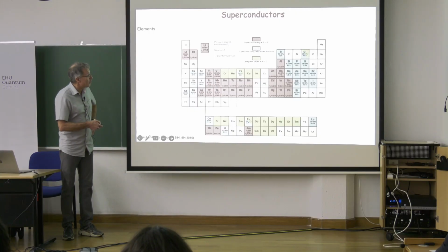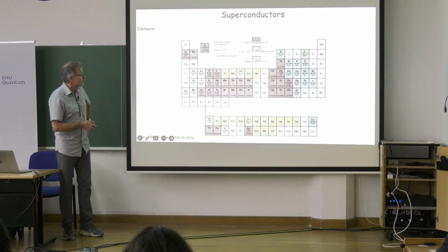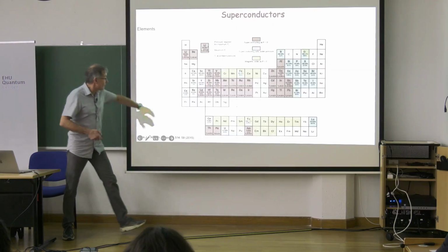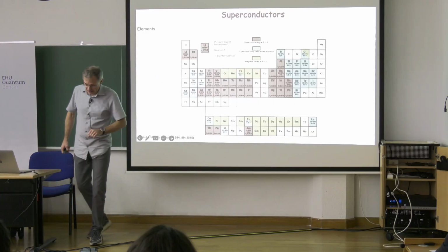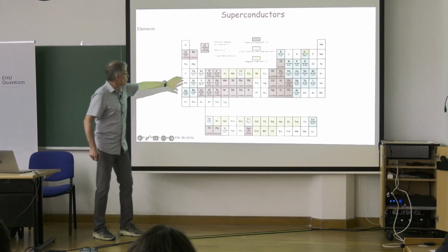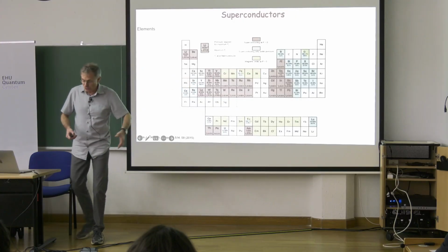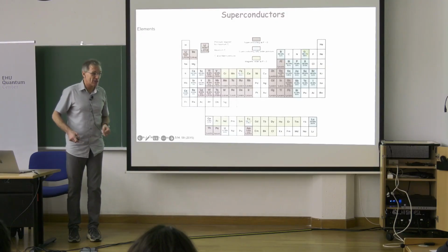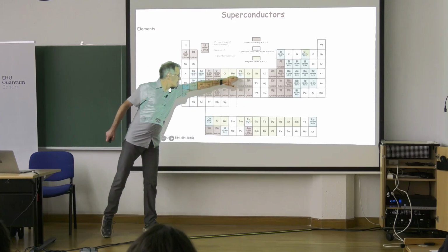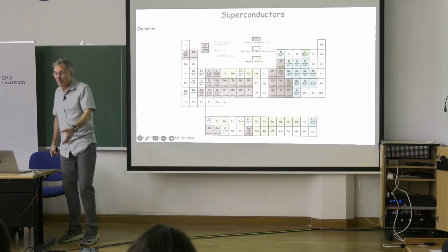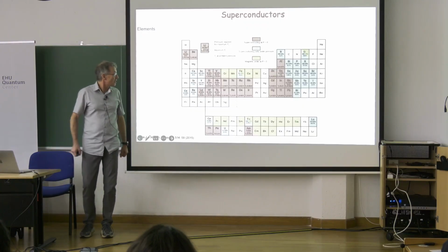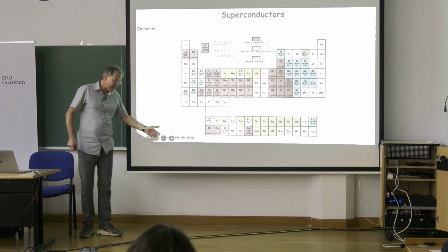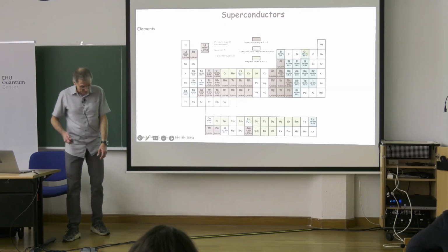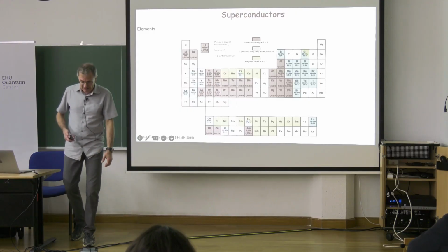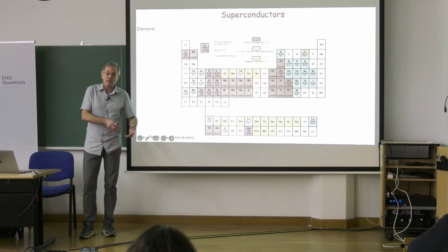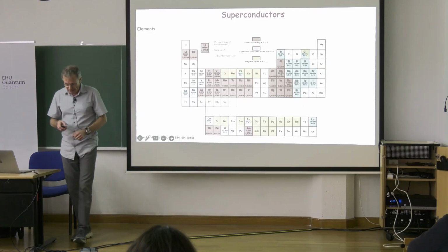only white and green are not superconductors. So brown is superconductivity at ambient pressure, and blue is superconductivity at high pressure, which shows that if you press high enough, then almost everything becomes a superconductor, even iron, which is a magnetic ferromagnet, but if you press it high, then it becomes a superconductor at a relatively high temperature, like 2 Kelvin. And these elements are usually clean, and they're usually type 1 superconductors where magnetic field is expelled.